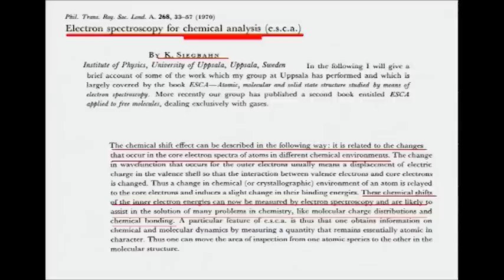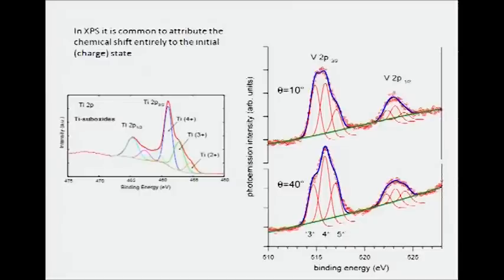Now, just to go back to ESCA, this is a little review from Kai Siegbahn in Physica Scripta in 1970. It's actually just a little review of the books that had been published some years before. And of course, it's stressing this chemical shift. ESCA is all about chemical state identification as opposed to simply elemental identification. And it was very much about spectral fingerprinting, to use XPS or ESCA as a spectral fingerprint of elements in specific chemical environments. And indeed, if you look at a lot of XPS literature, particularly from people doing surface analysis, you see these chemical shifts.